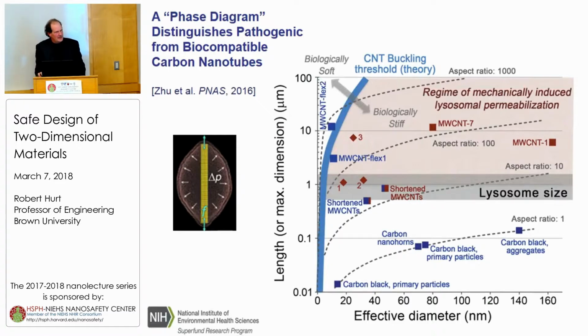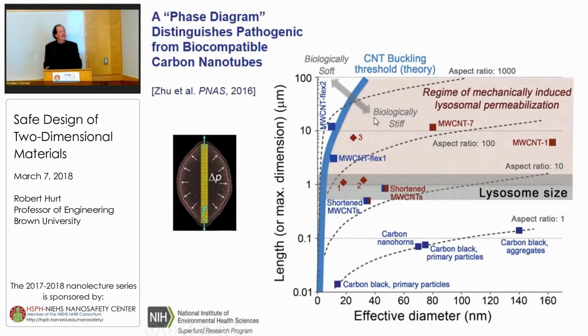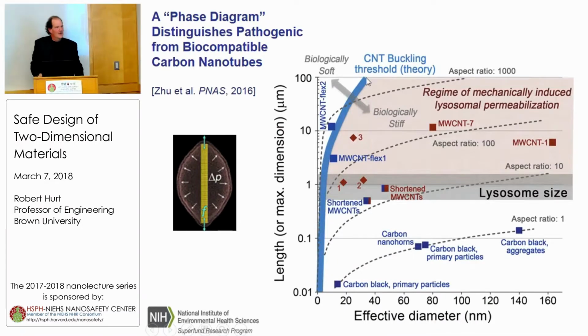But they also have to be stiff. So while these nanotubes are pushing on the lysosome, the lysosome is pushing back. And if they're too thin, they will buckle inside the lysosome. And then they won't present themselves to this biological system as a stiff fiber. And that's an old mechanics buckling problem. It's not that much different than looking at the beams in a building. And the taller and thinner the beam, the less force it can accommodate without buckling. And so this is the Euler buckling theory. And that line is this thick blue line on this plot. And tubes that lie on this side of the line are thinner or longer, some combination, would be what we call biologically soft.